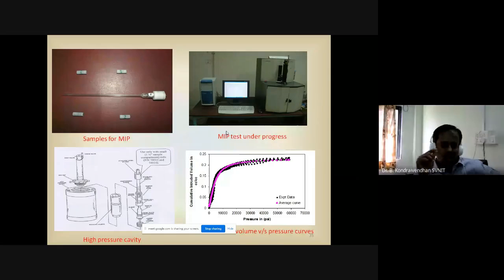Okay, this is the actual penetrometer cell. Whatever sample we cast, after hydration arrestation, the samples should be like this. Now you have to keep this sample inside the cell, at the stem part. Then you have to put this cell inside the low pressure station. Then we have to apply pressure up to 50 psi using the attached Corovin software.